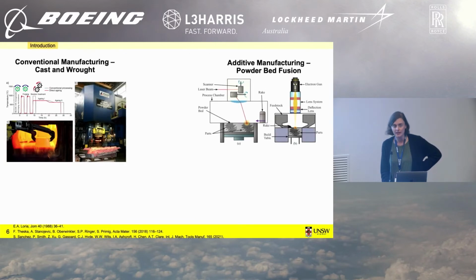So let's look at how we can make modern aircraft engine parts. So there's obviously conventional routes. This is a photo from an industrial partner based in Europe. So it's actually massively complicated, and conventional processing requires large plants. So you need to cast these materials, you need to remelt them often 3 times, you need to undergo a complicated multi-step forging procedure at high temperatures, and at the end you need to apply a thermal treatment to get amazing properties. However, nowadays there's obviously new ways of doing that via metal additive manufacturing, and my team is very often interested in powder bed fusion, so more on that later.